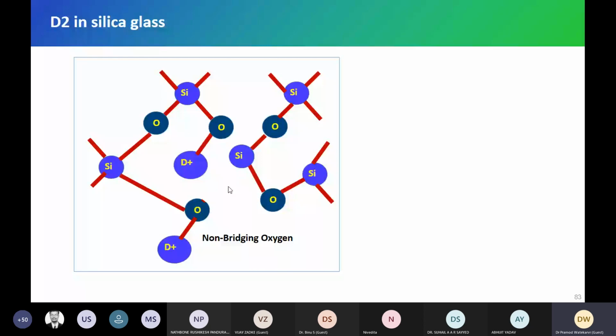1.3 is our useful band, and 1.38 is very near to it. So OH is very bad for communication. So if you replace it, the non-bridging oxygen bond is made with deuterium, and all these empty spaces are filled up. If hydrogen enters there, it has no place to bond with. Oxygen is all occupied by deuterium, and deuterium makes attenuation at 1.9 micron, not at 1.55 or 1.3. So it won't affect our optical communication. This way we can avoid the problem of OH attenuation in future because of hydrogen.